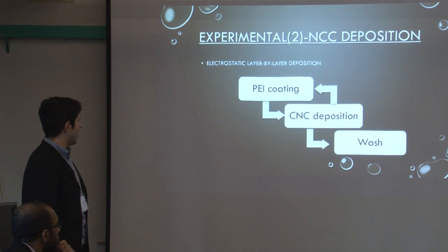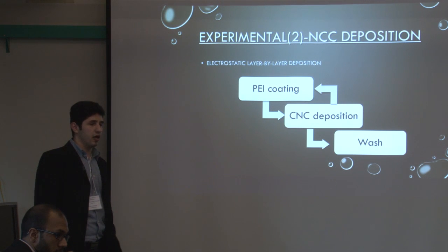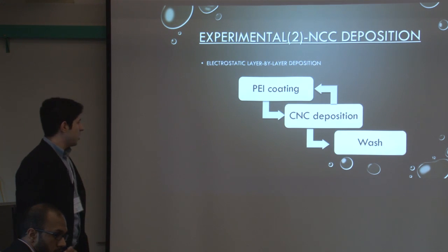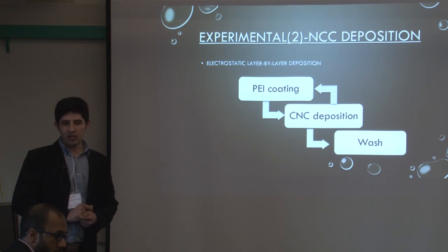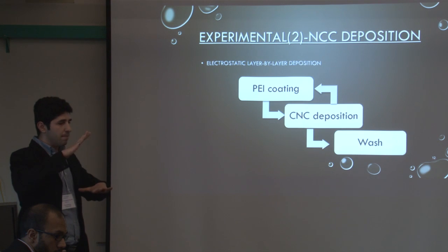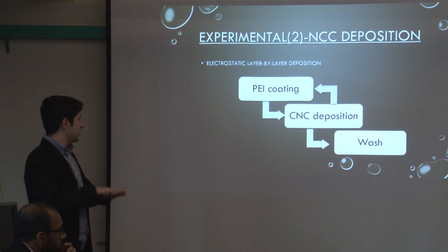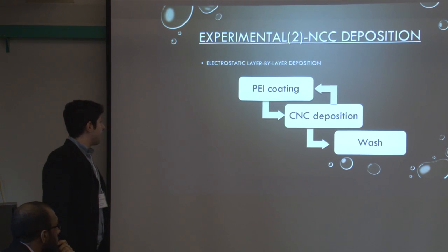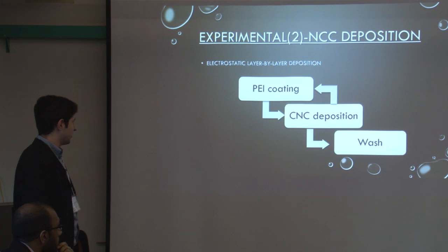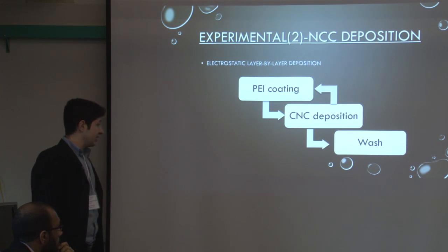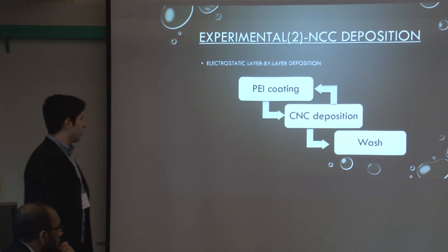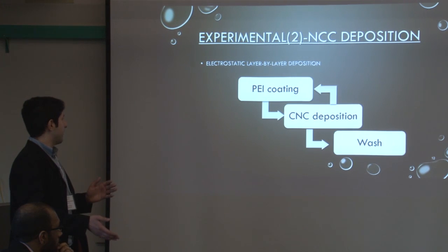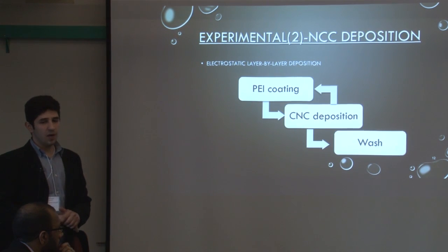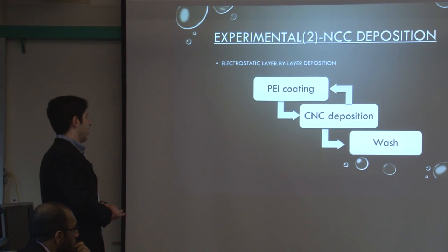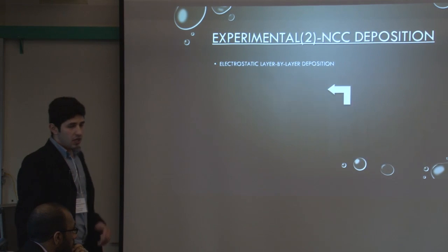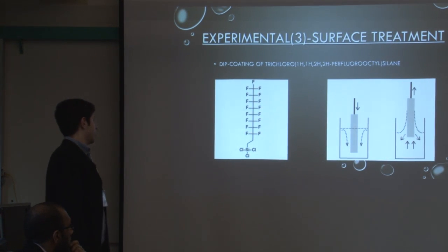The next step was to deposit the CNC, or cellulose nanocrystals, on top of our nanostructures. We did that using electrostatic layer-by-layer deposition, which allows us to have several layers of these crystals on top of one another. So using the PEI, which carries a positive charge, and knowing that our CNCs are previously functionalized with carboxylic groups, which are negatively charged, we deposited CNCs up to 5 layers on top of our glass substrate, and at the end we were able to wash the surface off.